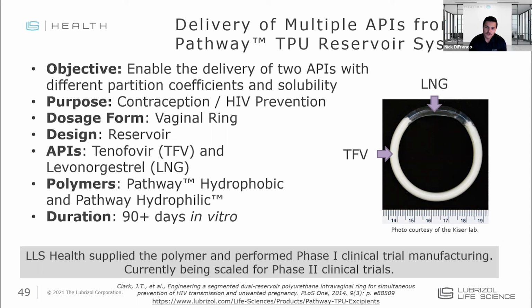The levonorgestrel component along the top of the ring is actually a co-extruded core sheath system of 2 TPUs. So the levonorgestrel is loaded into the core TPU, co-extruded with a sheath of a second thermoplastic polyurethane that was optimized to achieve the desired release rate for the levonorgestrel. So tenofovir, which was releasing, I believe, at a third of the rate of the levonorgestrel, we were able to achieve the targets for both of these at 90+ days in vitro, despite the huge differences in API properties, and from a single device on top of it all.